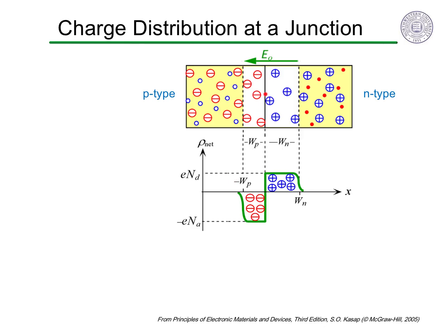On the p-type side with no holes in the depletion region, the negative charge density can build up to the concentration of acceptor dopant atoms times the electron charge. We then show it relatively constant until the depletion width Wp. While on the n-type side, the donor defect concentration determines the maximum charge density, which persists approximately to Wn.